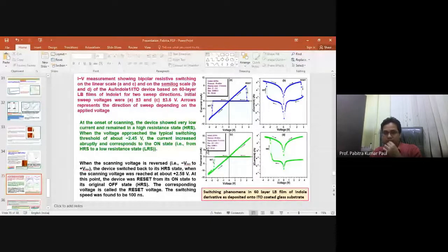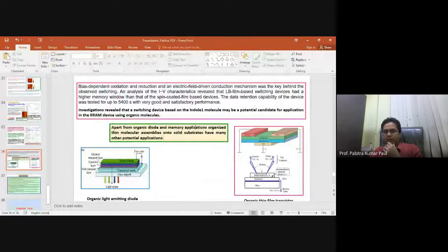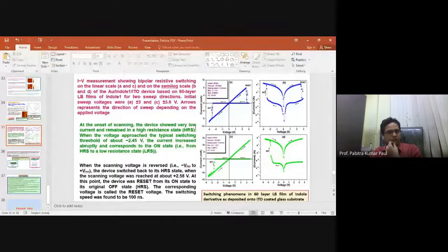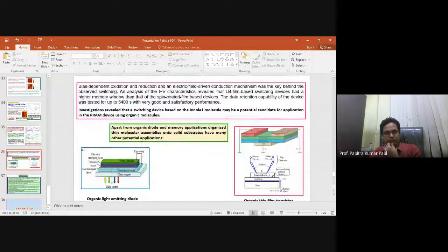This is the change in the current with the bias. Basically what happens internally is that the molecule undergoes oxidation and reduction with the change in the bias. So the bias dependent oxidation reduction, and then the electric field driven conduction mechanism, was the key factor behind this switching. IV characteristics revealed that LB film switching devices had a higher memory window than spin coated films. I have compared, though I have not shown it here, and the data retention is very high, 5400 seconds.